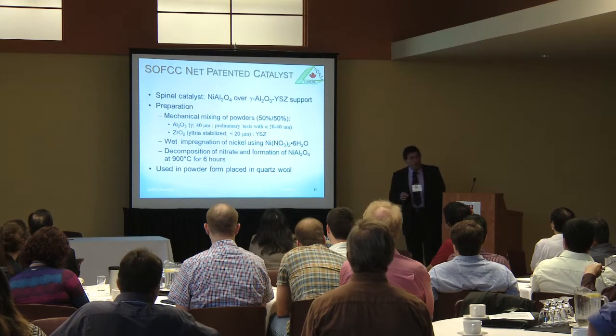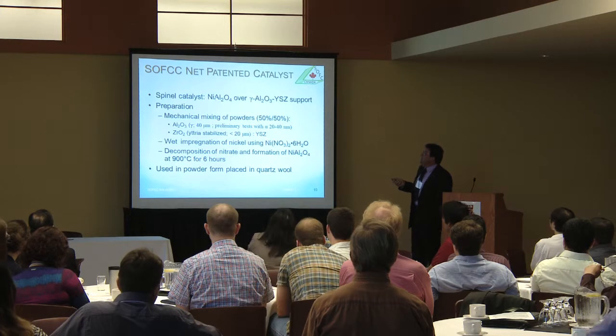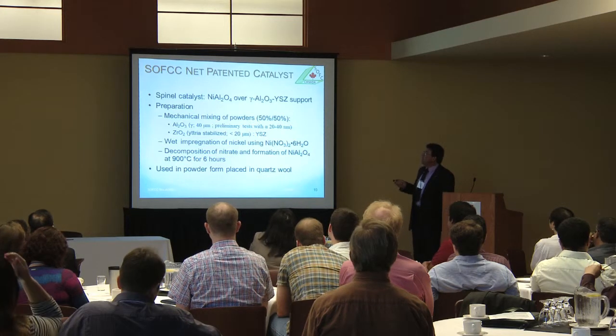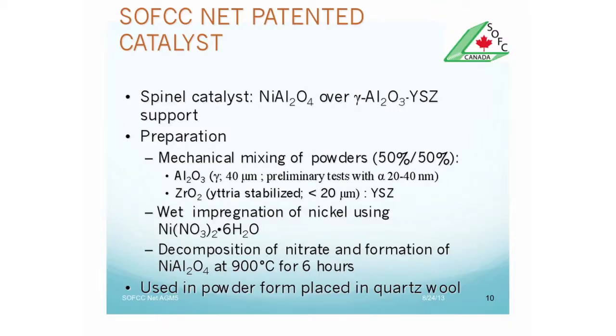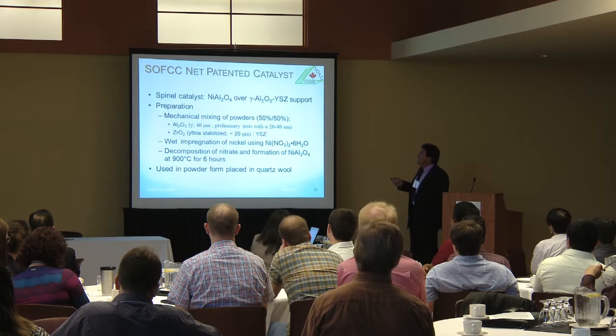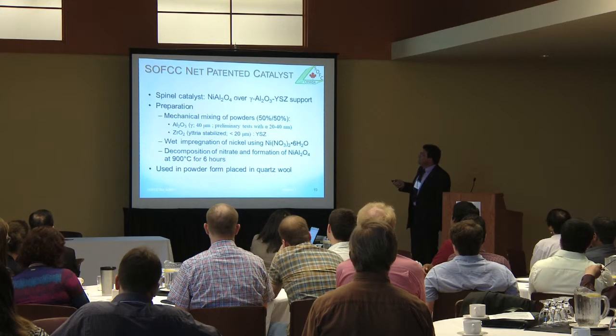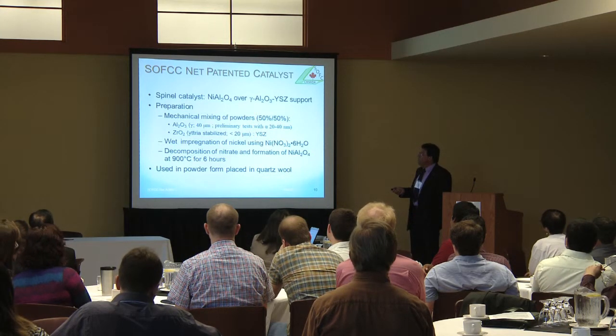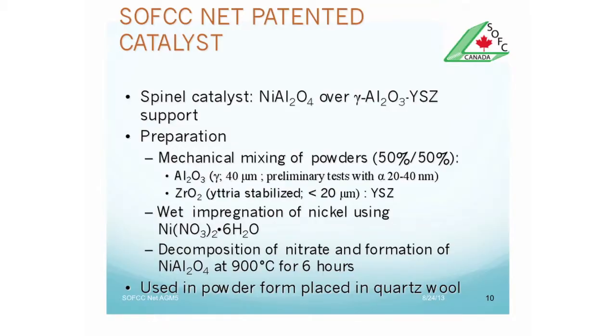So in our work, I will not go into details, but I will explain how we have worked on this. The decision was taken to work with spinels, at a moment when all the literature indicated that spinel is not a good phase to make a catalyst. Spinel is instead a nuisance for the catalyst. We decided to check the spinel efficiency, and we have prepared this on gamma alumina and yttria stabilized zirconia support.